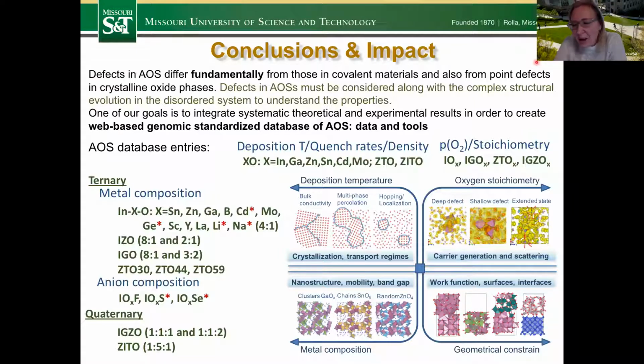That's a very good question, and we didn't look at many specific cases. Here you can see that there are several cases. We looked at crystalline silicon covered with the oxide, and molybdenum oxide with indium oxide interfaces. Of course, from the point of view of modeling, it's very hard to model the roughness, right? We really need huge supercells to do that. But at the same time, from the smaller cells that we've seen, we do have the oxidations, and we're also seeing the coverage, and having the amorphous material really helps because of that. Again, reconstruction and readjustment in the structure helps significantly to grow an amorphous layer on top of a rough crystalline layer.